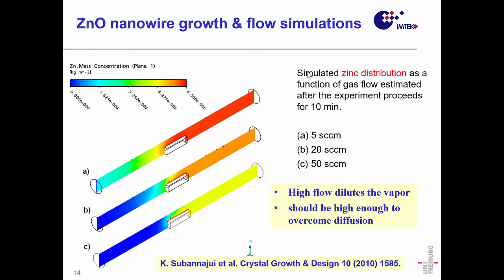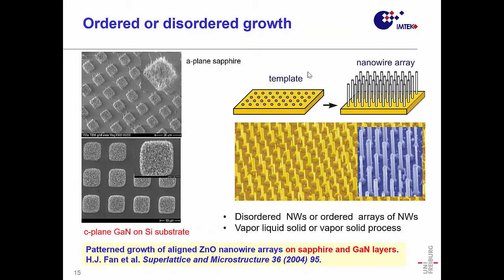Okay. So what else do you have to think about to control this? You have a tube furnace, and a lot of people report you can grow the wire opposite to the flow. You have an inert gas which transports your evaporated material to your substrate, and by the gas flow you are diluting that. And you have two processes. At high temperature you have diffusion, and diffusion also goes opposite to the flow, and that means you control by the flow how much of your gas comes to the point of your substrate. You see it here in a simulation done by ANSYS for different flow rates, and in this way you can control it so that you have a homogeneous distribution of the gas over your substrate in a really well controlled way.